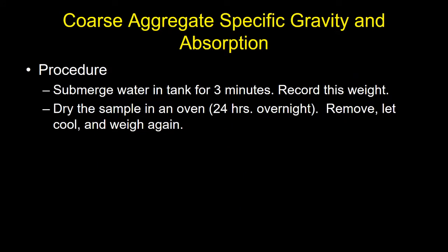So then after you've gotten that SSD, you've already dried off the aggregate lightly with a towel on the outside. You record that weight. After that's done, you submerge it in a tank for 3 minutes in that basket hanging under the scale or the balance. And after 3 minutes, you record the weight. That's going to be your submerged weight.